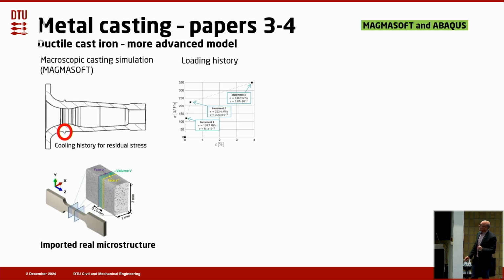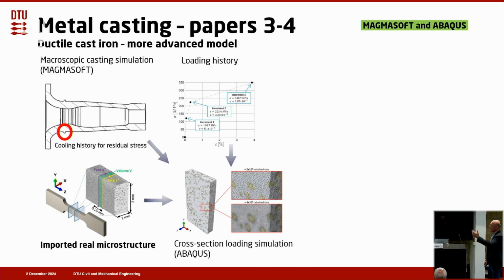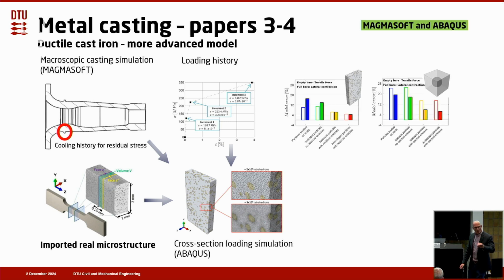Then we made a more advanced model where we did a macroscopic casting simulation in MagmaSoft, so we got the cooling history. That's very important for the residual stresses. And then we imported the real structure from the test specimen. We had this loading history there, and then we did a cross-section loading simulation in Abaqus. And with that, we got a much more realistic description.